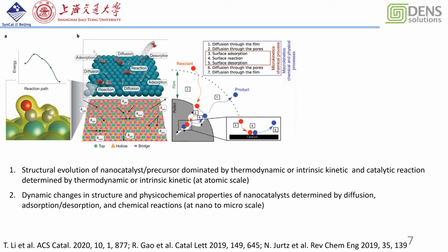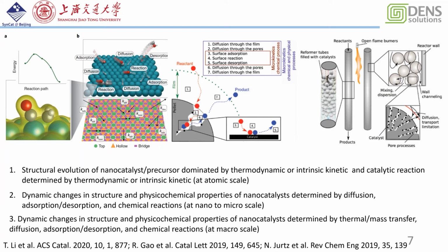But the worst is the last one. People come here wanting to use the in-situ technique to do research because they found something very interesting in the fixed bed reactor. In that case, several grams of catalyst were put in the reactor, and they showed a very beautiful catalytic performance. But what dominates the catalytic performance is not even the diffusion, it is heavily related to the mass transferring and the thermal transferring.